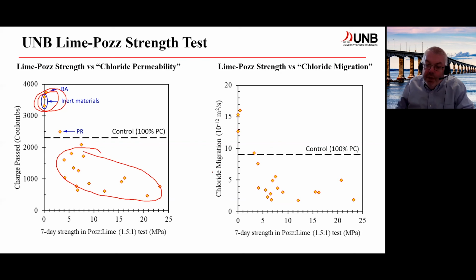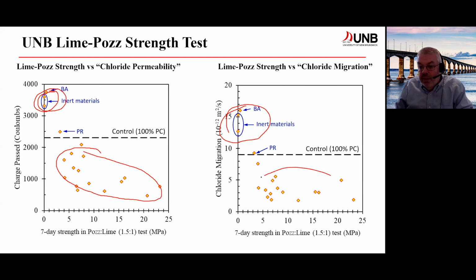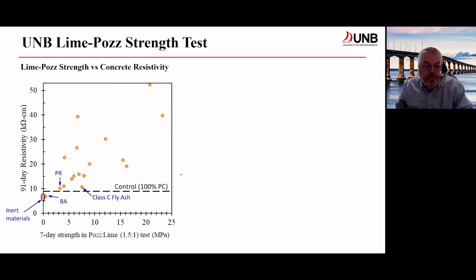So this is a real chloride test. We're actually measuring the penetration of chlorides into the concrete in this test. And again, we see our inert materials perform badly, both in concrete and in our pozzolan lime test, whereas materials that perform well do so in both tests.